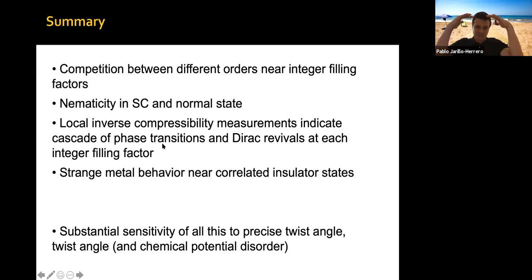This is the parent state out of which all the ground state and many body physics at lower temperature occurs. There is strange metal behavior near the correlated insulator states. And more importantly, as was emphasized very nicely in Eli Zeldov's talk, there is substantial sensitivity of all of this to the precise twist angle, to twist angle and chemical potential disorder, and other parameters that you can vary in the system, okay?